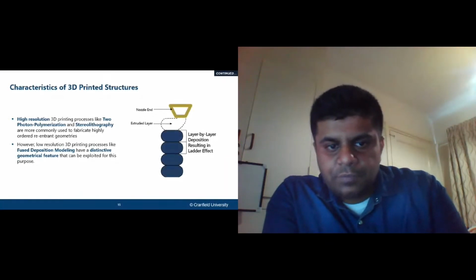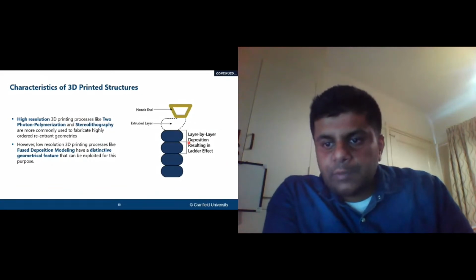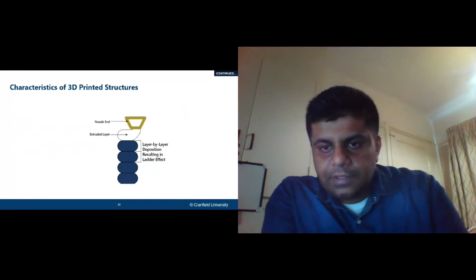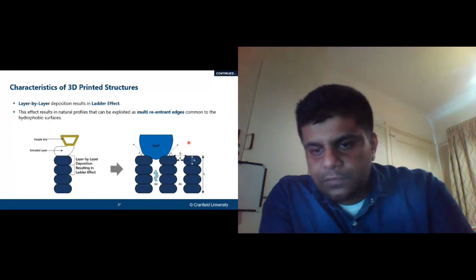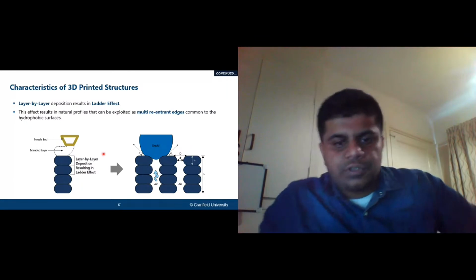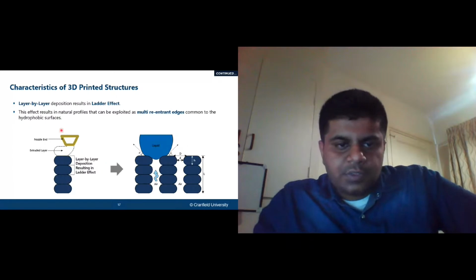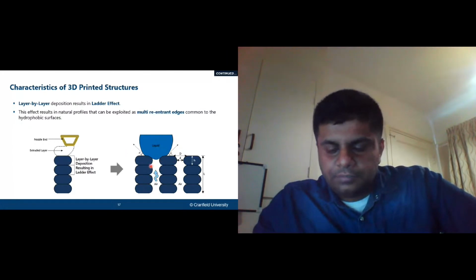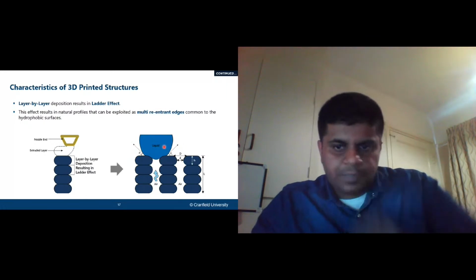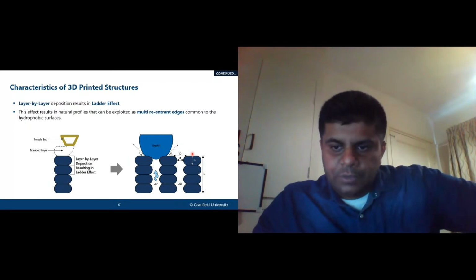So how do we go past that? We actually study this layer by layer deposition effect, which is also known as the ladder effect in literature. This distinctive geometrical feature, known as the ladder effect, can actually support air to be filled like this. So you have multiple layer by layer deposition, as you can see over here. This is your extruder, which is going to be depositing the extruded layer. Once you have this, you're going to end up with a layer by layer deposition structure as shown over here. And if you stack multiple of them together, you're going to end up with a porosity over here, where you can trap air or some other fluid, in which you can easily generate your superhydrophobic behavior as shown here.